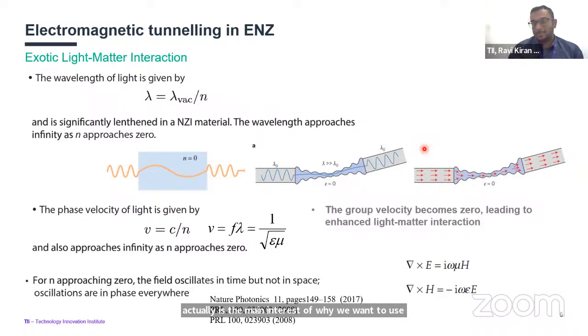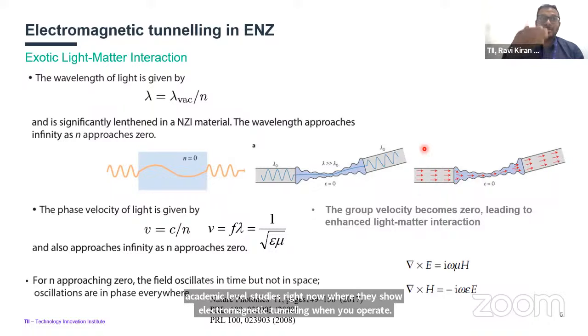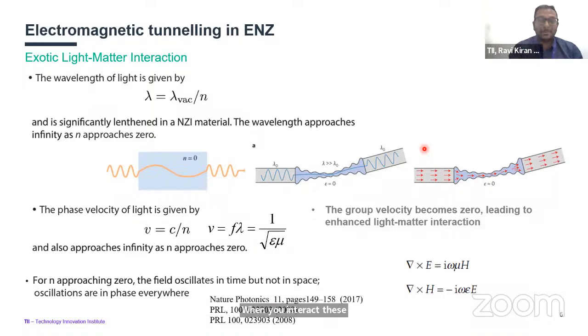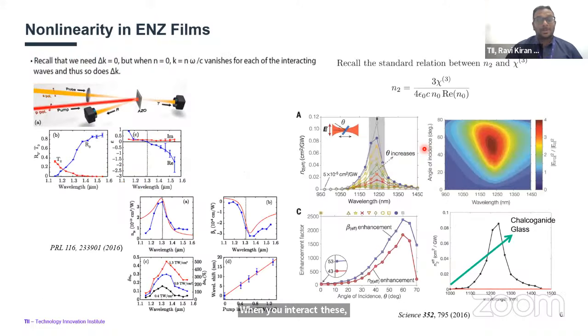And there are several academic level studies right now where they show electromagnetic tunneling when you interact these thin films with a particular wavelength of light where the epsilon goes to zero. The nonlinearity in these films is enhanced, especially the chi3 nonlinearity. So if you look at this equation, the N2 is the Kerr nonlinearity, and it is inversely proportional to the real part of the refractive index. And when that goes to zero, the N2 goes very high. And this was shown quite recently in AZO films as well as ITO films.